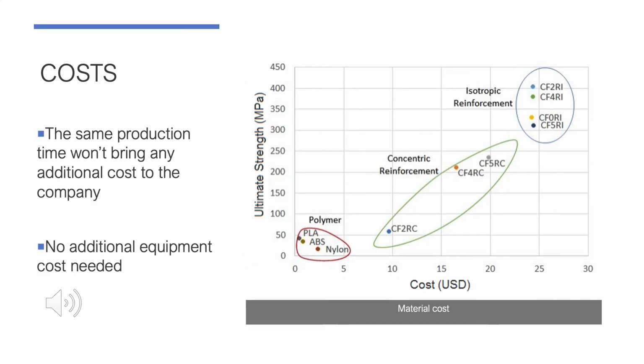In this slide, we'll talk about the cost. The effect of fiber orientation on tensile properties versus cost is shown in the figure. The group of isotropic reinforcement materials shows the best ultimate tensile stress, with a mean of about 350 megapascal, of course with the highest price. The group of concentric reinforcement materials exhibits moderate ultimate tensile stress, with a mean of 150 megapascal and a lower price of $15. And the traditional 3D printing polymers show low overall ultimate tensile stress below 50 megapascal, with less than $5 of material cost.